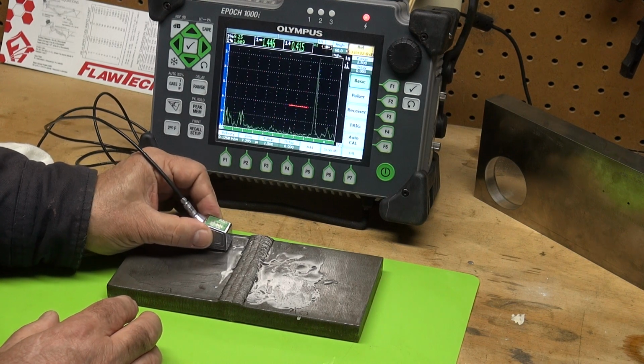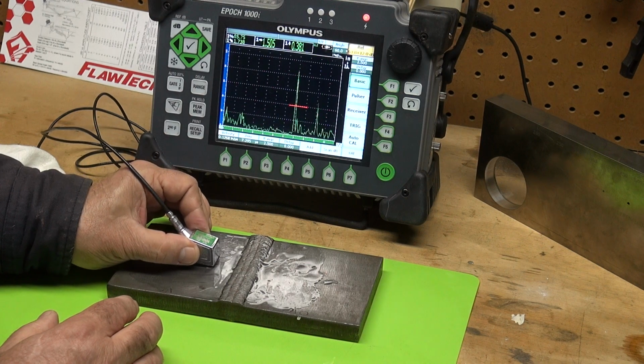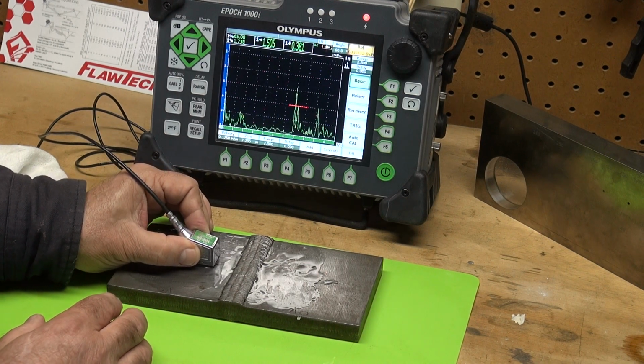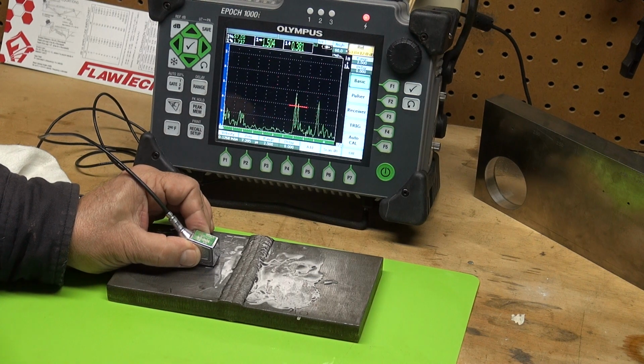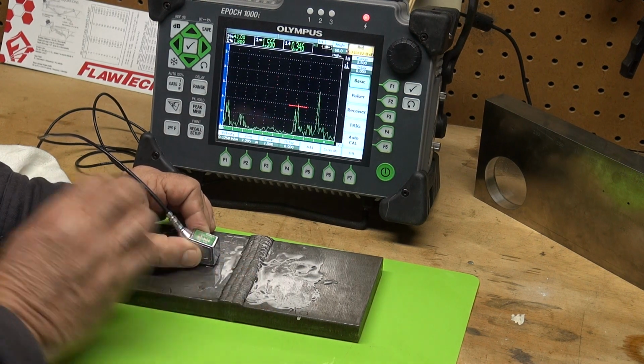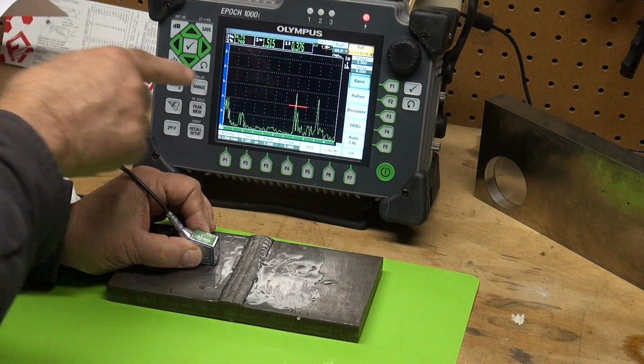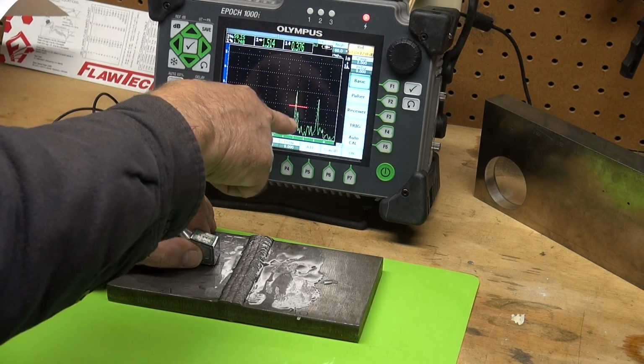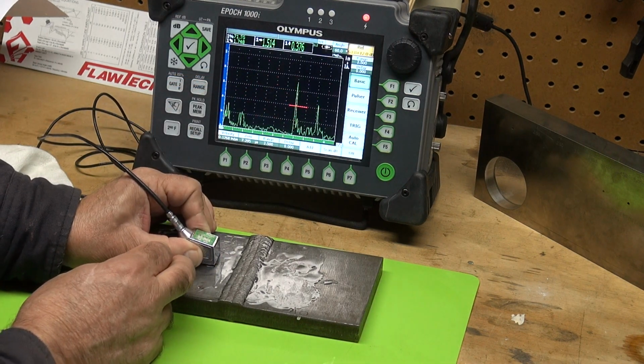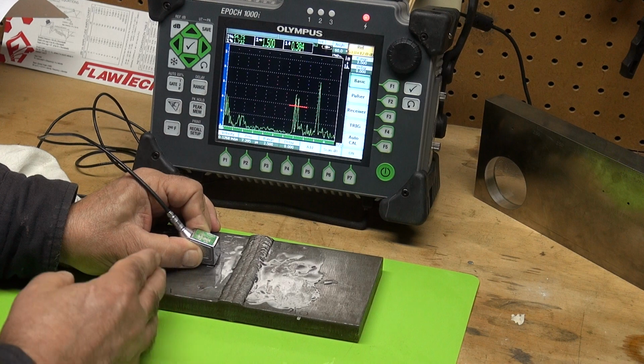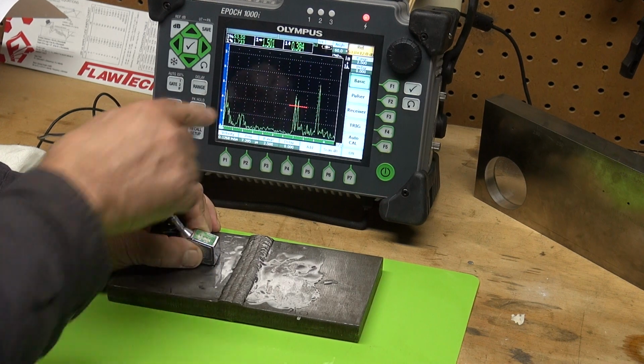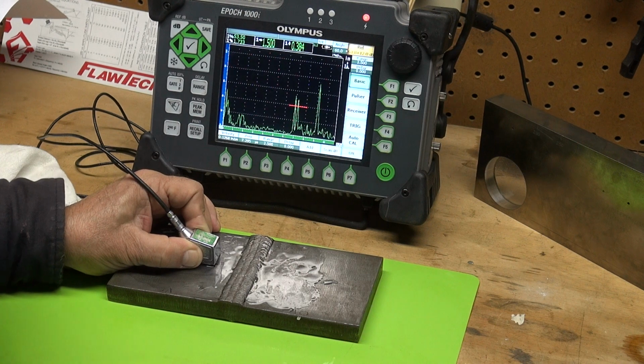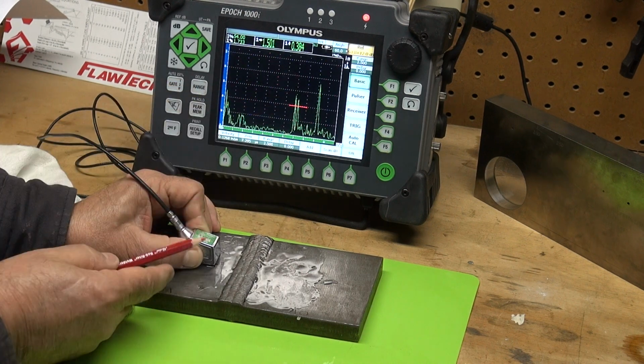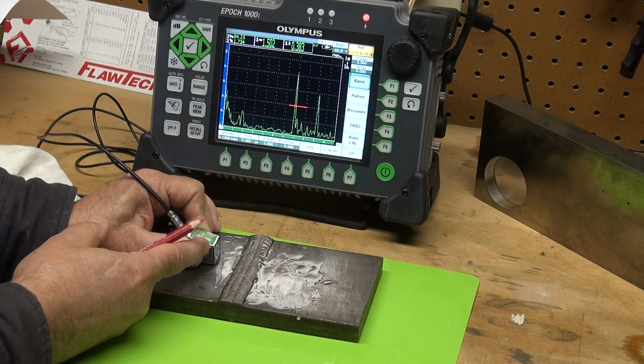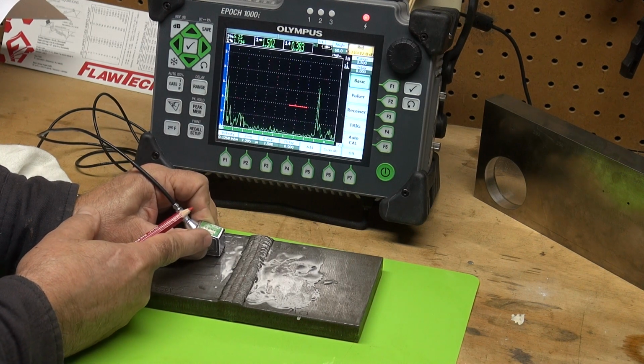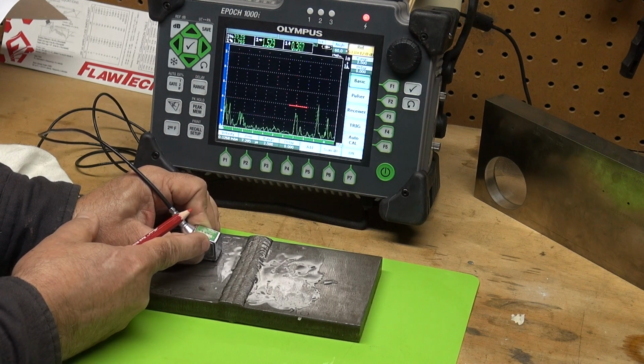Now, as I scan over right here, right in the middle of this weld, that is a slag inclusion. The slag inclusion is a volumetric signal, and you can kind of see some of the volume of that, but here it is. Let me move parallel to the weld. Right here is our defect, our slag inclusion. Now as I move parallel, we'll see it go away. There, it's gone. We're coming back into it.